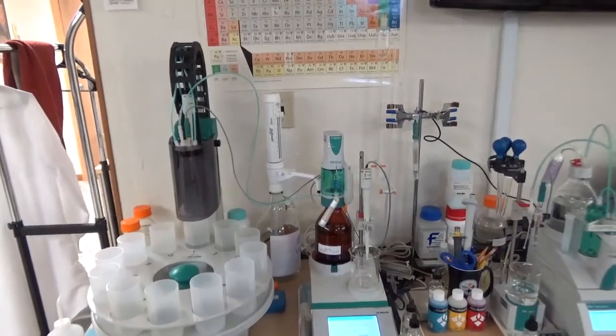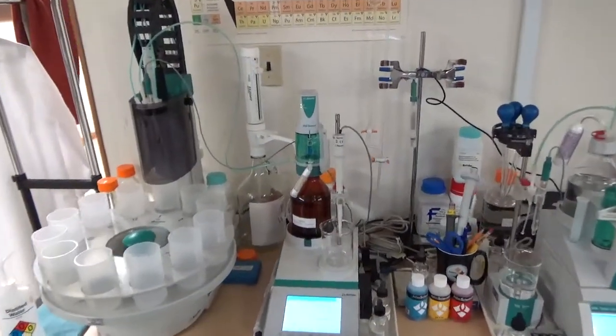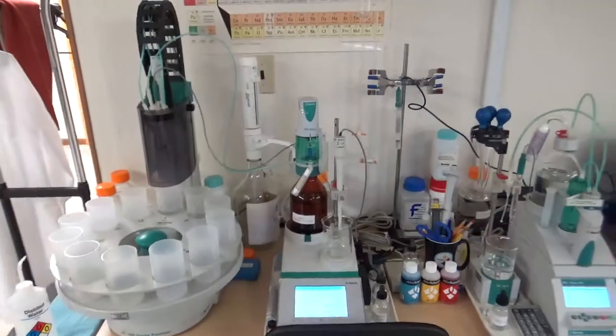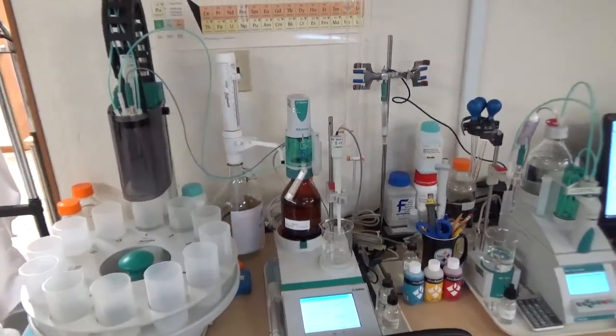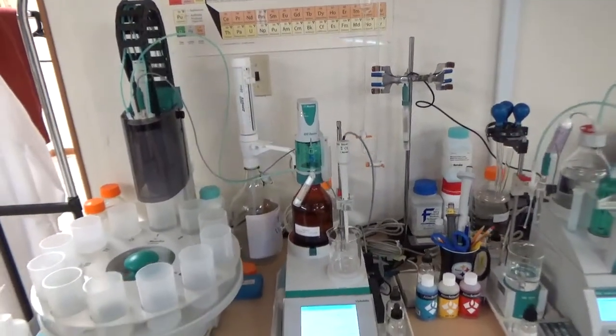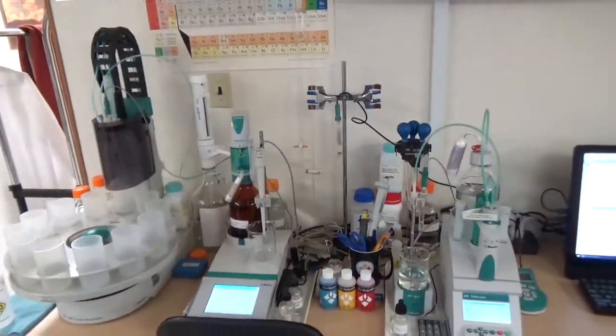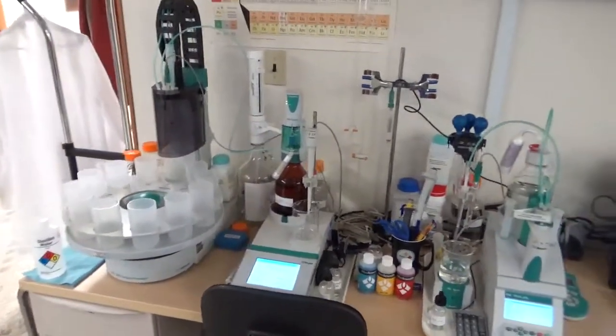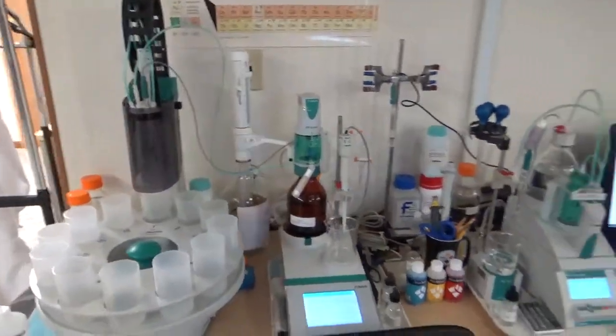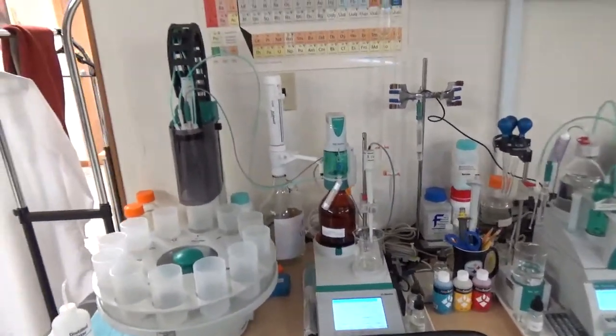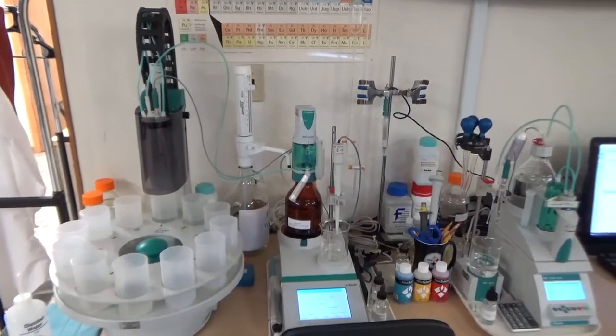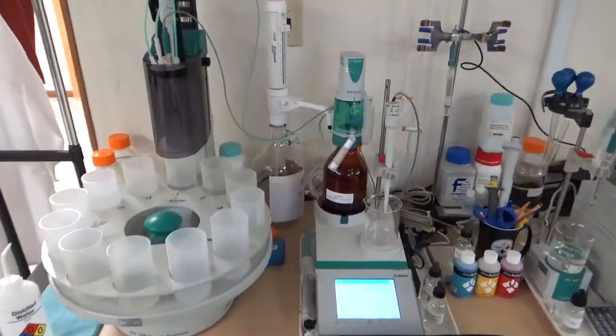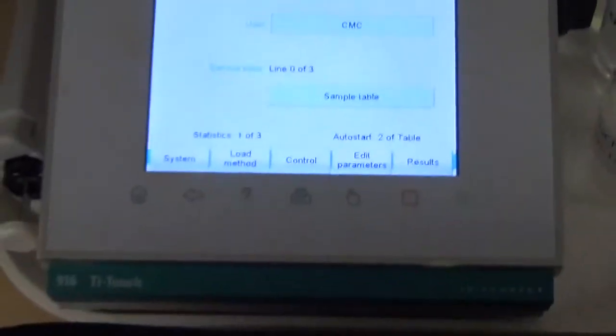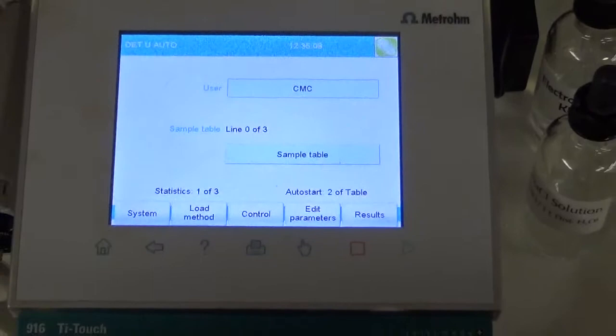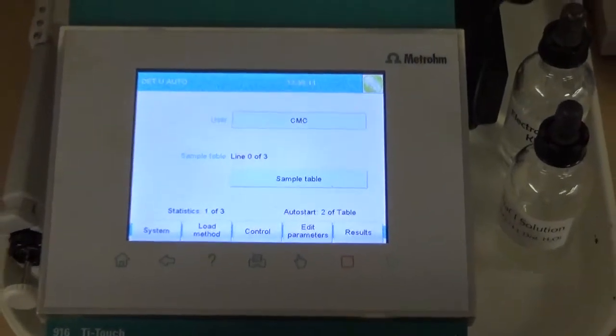We digest the concrete powder in the water or nitric acid to get the chloride, and then we do the filtration and we take the filtrate, and with the filtrate we do potentiometric titration of chloride against silver nitrate as a titrant to determine the chloride content. And here is a setup where we use Metrohm 916 Ti-Touch. It's a touch control titrator from Metrohm.